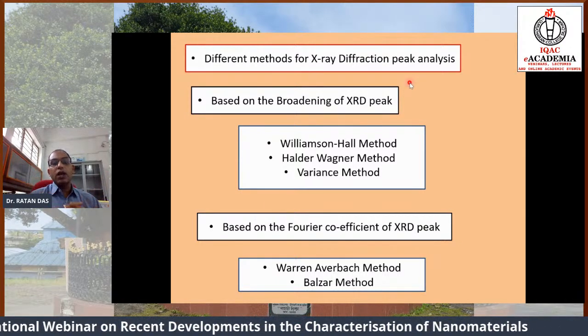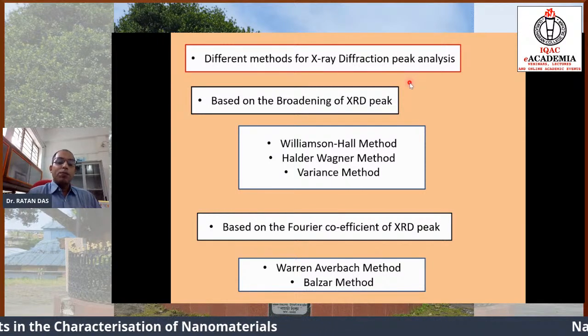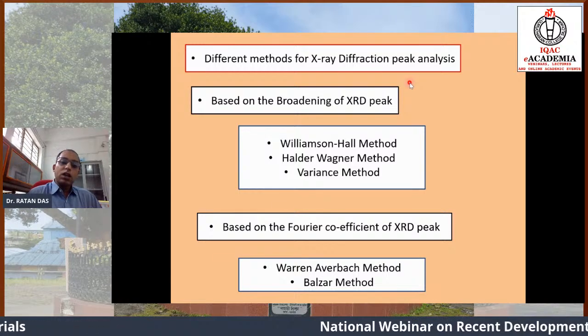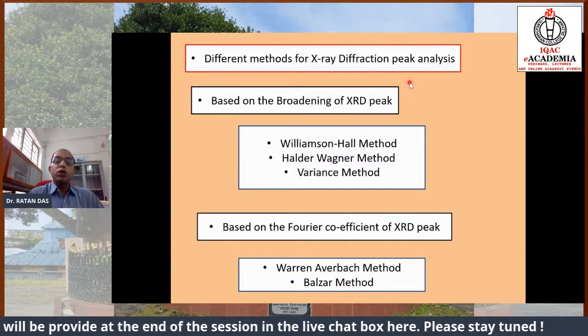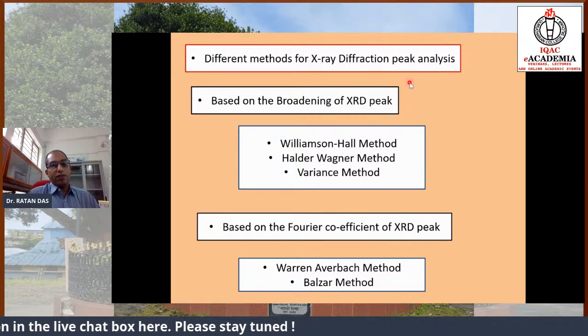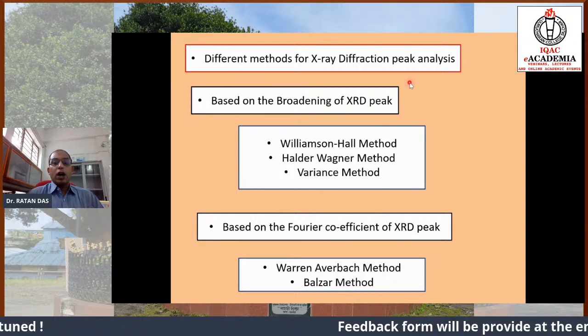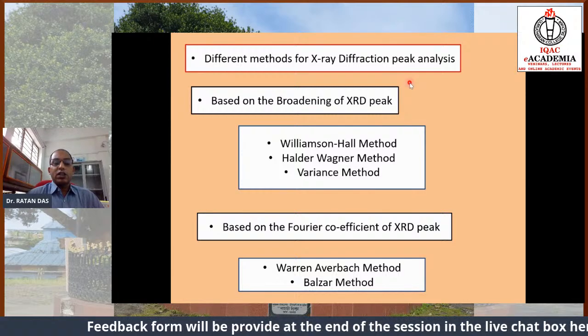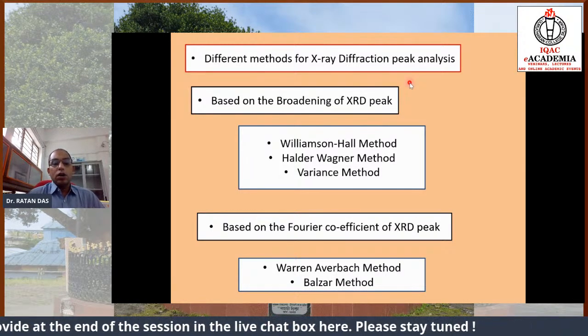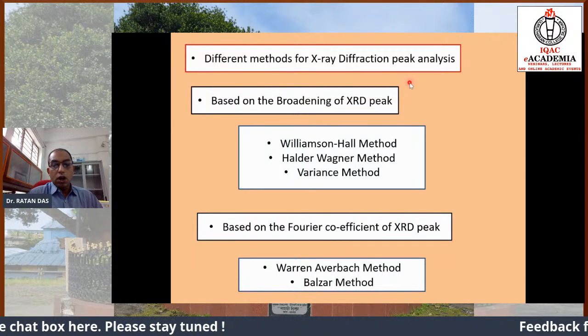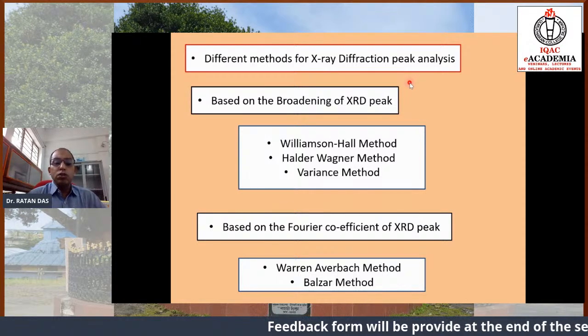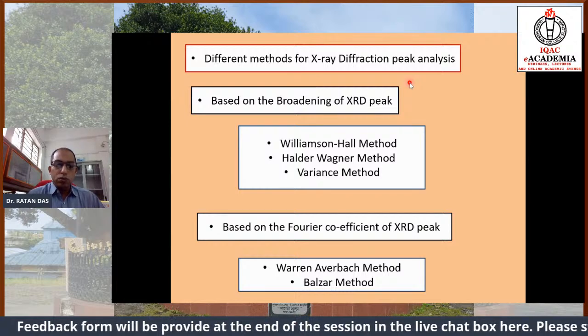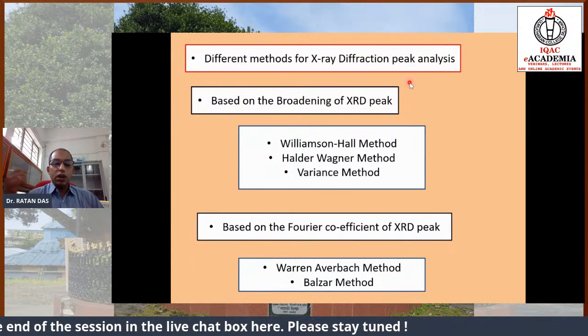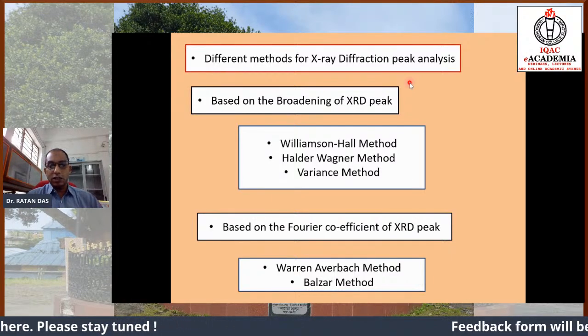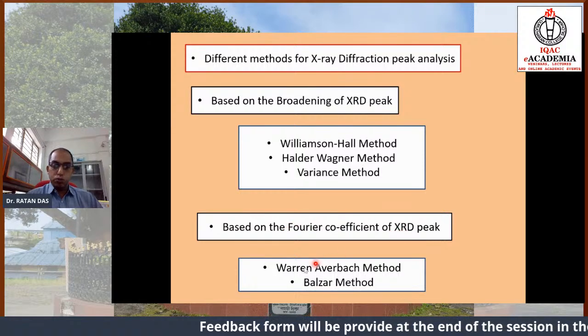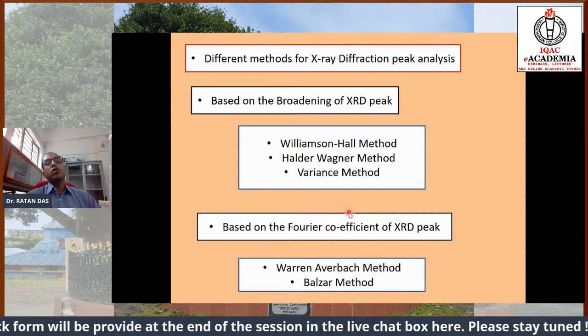Suppose the X-ray diffraction peak may be a Gaussian peak. Sometimes the X-ray diffraction pattern may be a Lorentzian peak, and sometimes there are also peaks which may be a combination of a Lorentz function pattern and a Gaussian function pattern. The Gaussian function, the Lorentzian function, or the combination of these two, what is known as the Voigt function, we do the Fourier transform of those functions, and after doing the Fourier transform, we may obtain the Fourier coefficient of the X-ray diffraction peak. So, analyzing the Fourier coefficient through the Warren-Averbach method and Balzar method, we may obtain also different information.